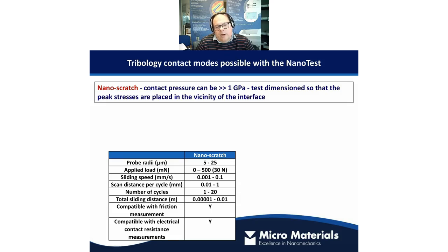We can do a single cycle, so normally that will be a ramped load scratch test, or we can do multiple wear tests where we use a subcritical load multiple times. And so typically we might go up to 20 cycles. So it's a small number of cycles, a small distance, but high contact pressure loading, so small tips and can be quite high loads. And of course we measure friction, and we can also measure additional tertiary signals as well, which we'll cover a little bit later on in the talk.